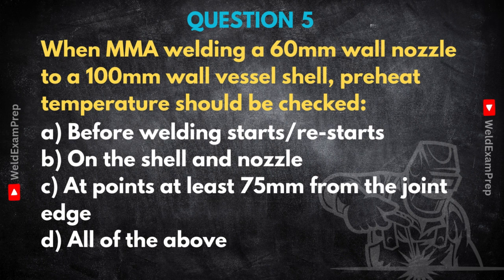Right. For a critical, heavy section joint like that, the comprehensive and correct answer is all of the above. All of them. Okay. Absolutely. This is absolutely not a place to cut corners. Each one of those checks is vital for the preheat to be effective. Let's break it down. First, checking before welding starts and restarts. That ensures the minimum required preheat temperature is actually achieved before you strike an arc, and critically, that it's maintained throughout. If welding stops for a break, the metal cools. You must bring it back up to temperature before restarting. Makes sense. Maintain the heat.